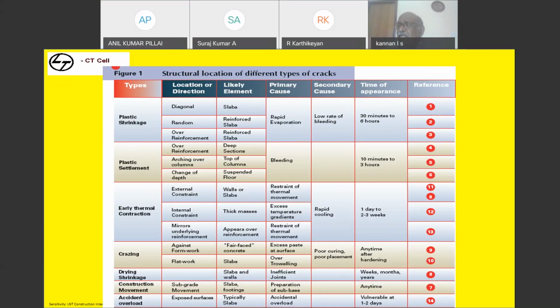To avoid this, see that the concrete is not over vibrated. Adequate vibration needs to be done, and wherever excess slurry accumulation is there, it needs to be replaced with good quality concrete, and slurry filling needs to be avoided. You need not worry about this. So this can happen even if you are not curing properly.